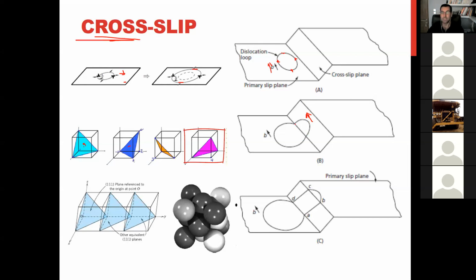Yeah, but in this part, here you can see this part and this part of dislocation, which is edge dislocation, the Burgers vectors is not inside of this plane, so cannot move. So when this loop cross to another slip system, a slip plane, just a screw portion of this loop can move. The edge parts cannot move. It become like this, just lines.